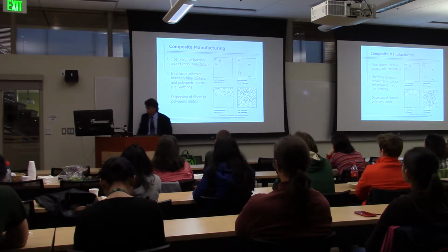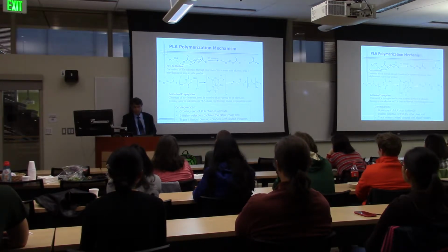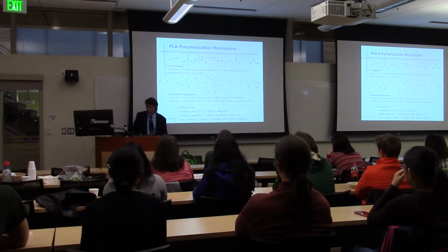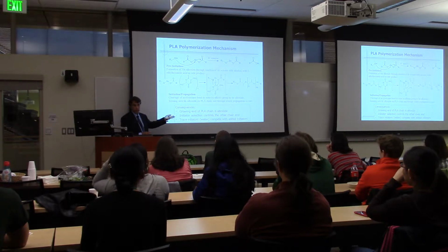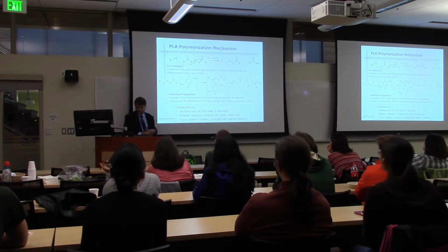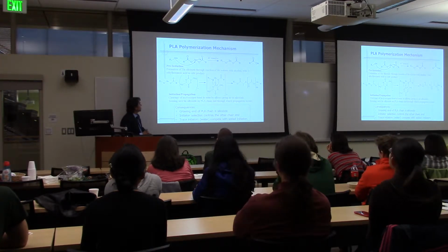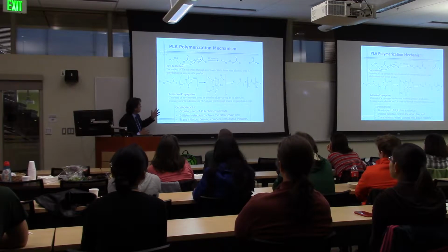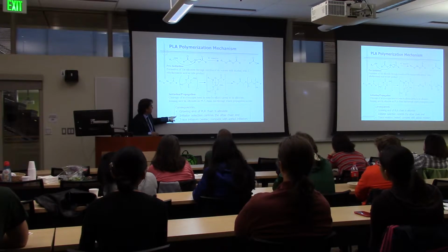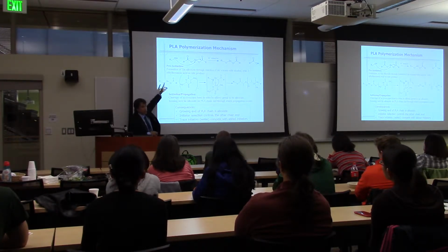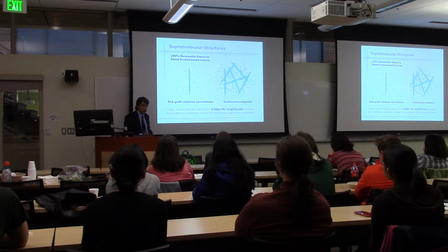And of course, if you want to get good dispersion, an easy way to do that is through manipulating the surface chemistry. And so the idea that we had is to actually decorate the cellulosic nanowhiskers with polylactide chains. Okay? And here I show the chemistry associated with the ring opening coordination insertion mechanism of using the traditional tin type of catalyst. And the details of the chemistry are not so important, but you should understand that really the initiator is what you'll find at the end of a chain, and it's initiated by an alcohol or a hydroxyl group. Okay? Well, if you know the structure of cellulose, you'll know that it has lots of hydroxyl groups associated with it, and so our idea was, can't we take this cellulosic nanowhisker and actually grow polylactide chains from it? And so we've been able to do that.